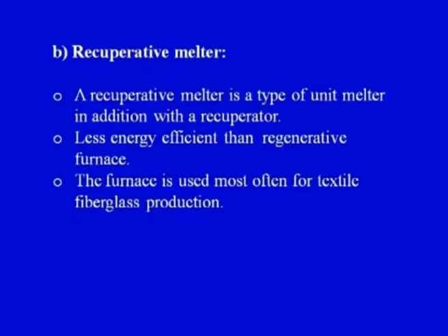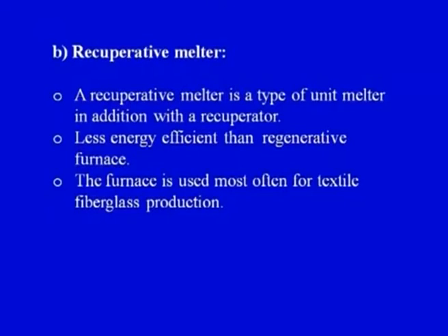The second one is the recuperative melter. A recuperative melter is a type of unit melter with the addition of a recuperator. So, here we have a recuperator which is not there in case of a unit melter, otherwise it is similar to a unit melter only. It is less energy efficient than the regenerative furnace. So, energy efficiency will be more than the unit melter, but it is less than the regenerative melter that we are going to see in the subsequent slide.